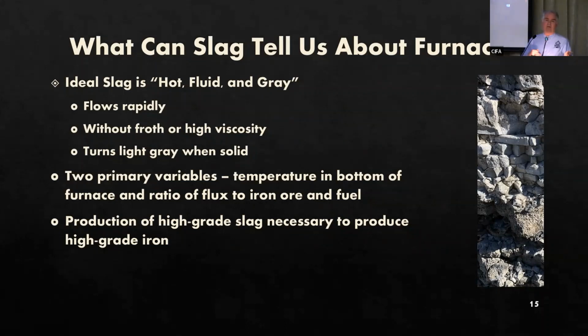They also looked at the characteristics when the slag and the iron were tapped from the furnace. For example, did the slag flow out rapidly or was it sticky and viscous? Did the iron emit sparks when it came out? Or was there scum seen on the surface of the iron when it was tapped from the furnace? All these were indications to the furnace workers about the relative temperature and the composition that was happening inside the furnace. So the furnace workers, and this is a key point, learned that to make high-grade cast iron, they first needed to make high-grade, high-quality slag.